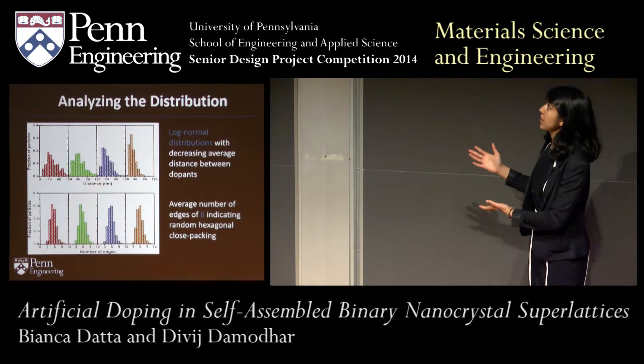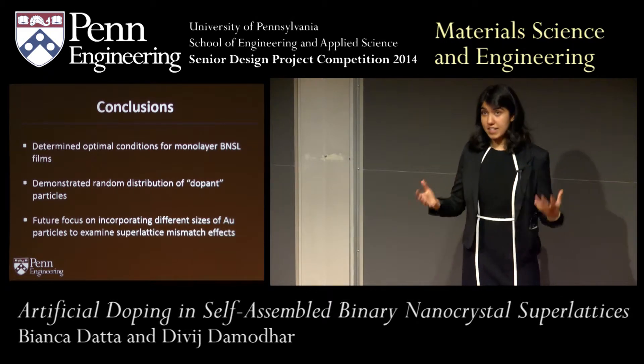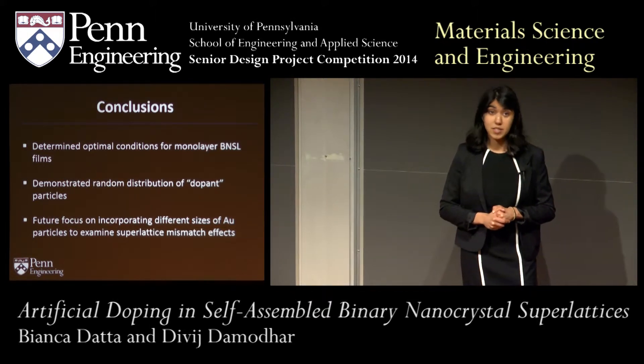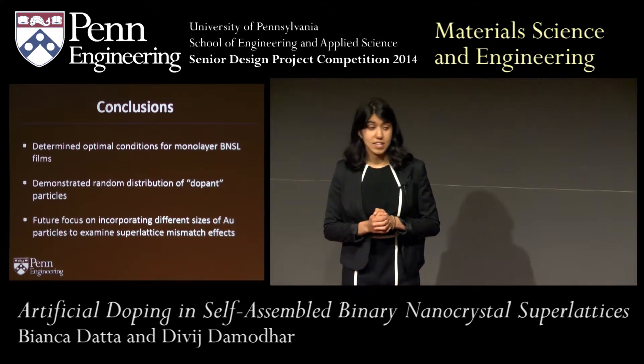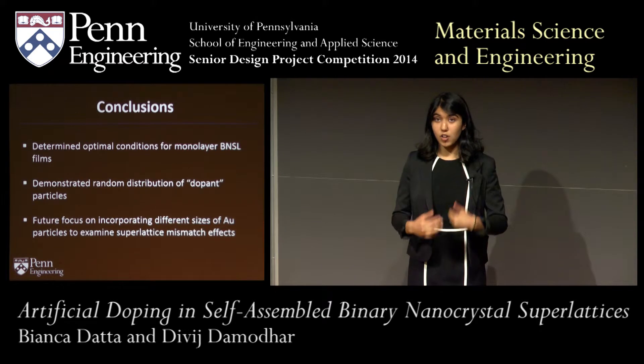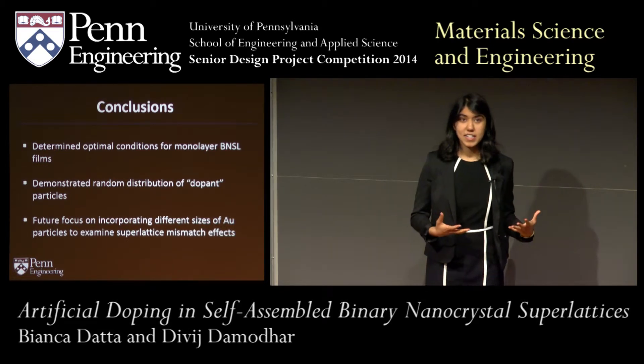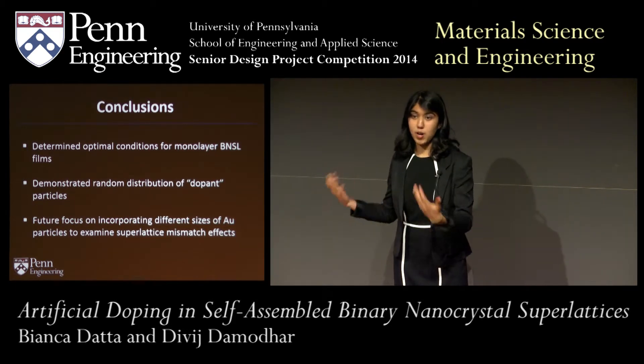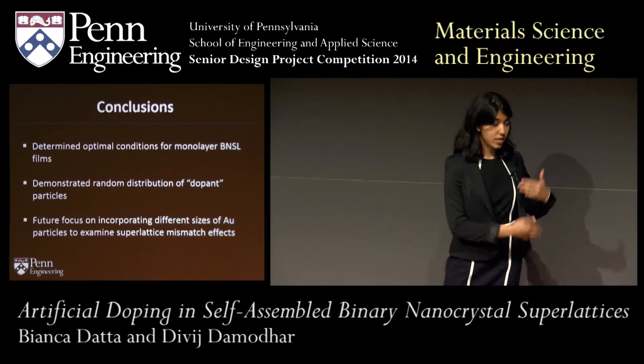We were able to quantitatively determine that there was a random distribution of dopants in these films. From our studies, we established the optimal conditions for monolayer formation of binary superlattices, which is something many groups have struggled with in the past. We also demonstrated a random distribution of dopant particles in these films, and we established that it would be interesting for future studies to examine lattice mismatch effects. In our studies we used gold particles carefully synthesized to match the exact size of our quantum dots; however, in future studies it would be interesting to try different sizes of gold particles to see how induced lattice strain would impart defect phenomena on these films, gaining fundamental insights into atomic phenomena observable in nanocrystalline form.